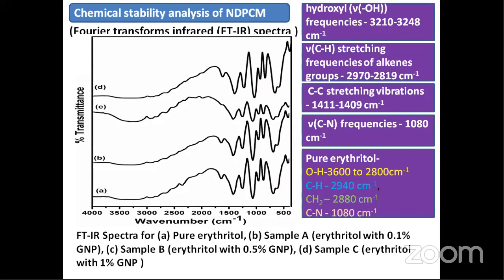Chemical stability analysis of NDPCM. The Fourier transform infrared spectra was measured in a range varying from 4000 centimeter minus 1 to 400 centimeter minus 1. These observed FTIR results suggest that there is no chemical reaction between erythritol and the graphene, as the change in all peaks between pure erythritol and graphene added erythritol is negligible.